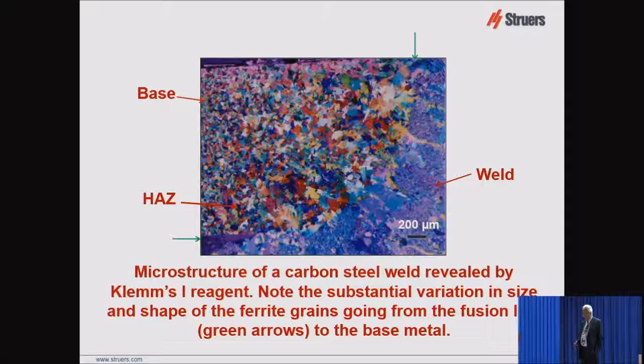Here's another carbon steel weld using Klemm's, and you can see the top edge here. There's a little corner down here, and this is the fusion line, and you can see penetration of the metal in this zone into the weld itself. We're dissolving the steel here, and this is all weld metal over here. We're at 50x, and you can see this penetration of the alloy content in the base metal going into the weld. And this, the base structure, original structure, is right here.